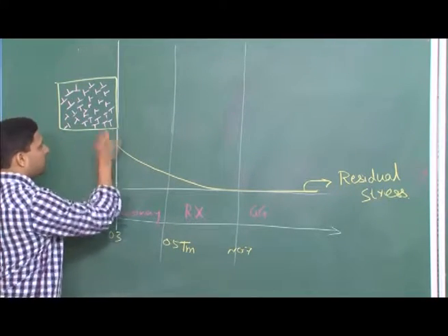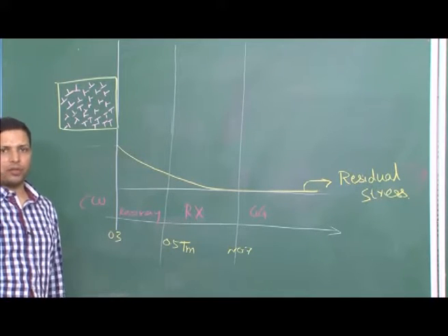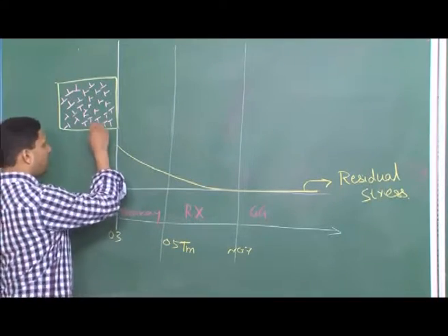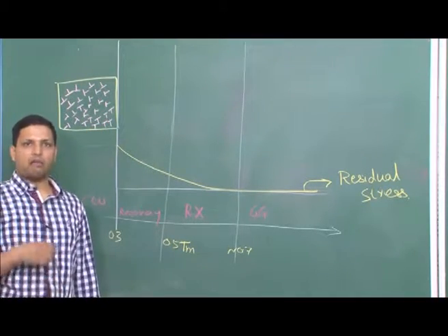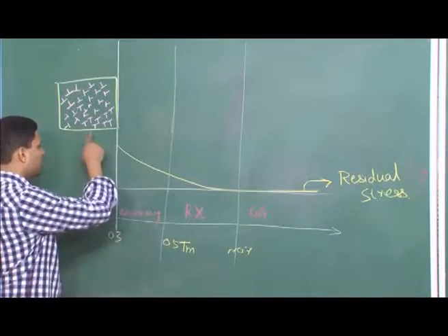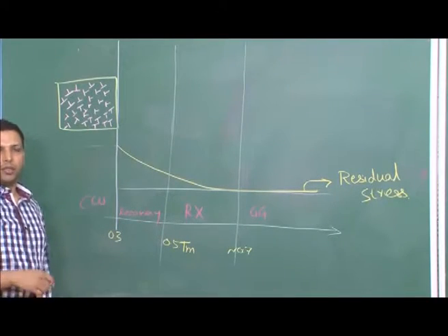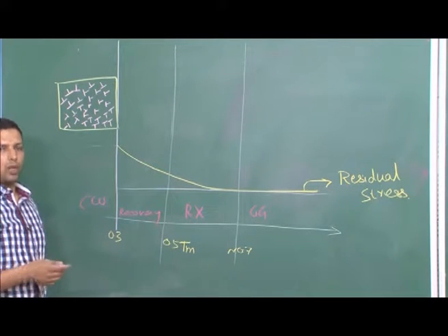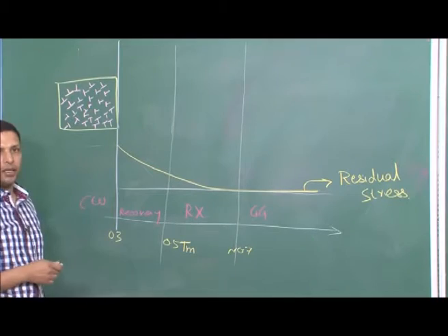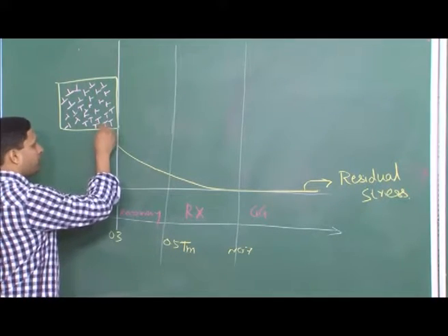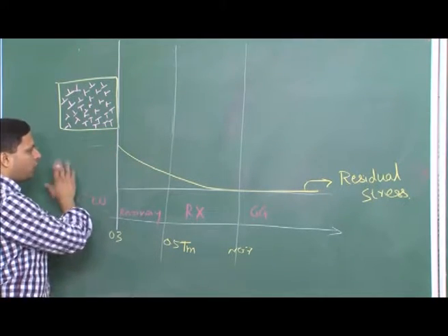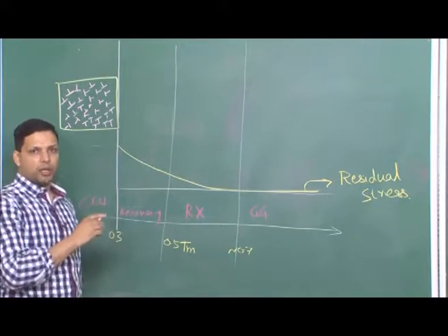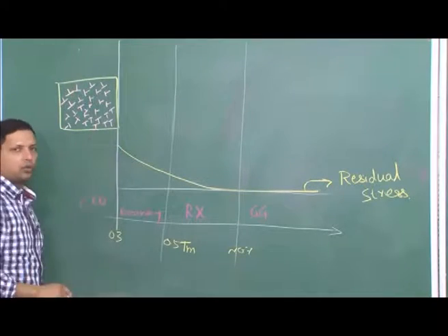So, in this temperature range, this is the kind of microstructure you would expect. Dislocations would be randomly distributed throughout, and it is because of these dislocations you have high strength, but since the dislocations are randomly distributed, you also have low properties, like low ductility, and at the same time, since it is cold worked and no residual stress has been removed, there is limited ductility to the material that you have deformed by cold work.